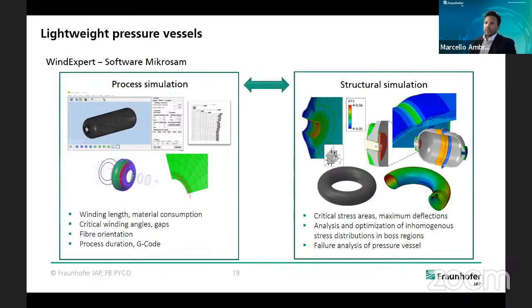So what we get from the process simulation is, for example, the winding length, the material consumption, critical wind angles, gaps, failures, the fiber orientation in each point, the process duration, and also the G-code for the machine. And in the structural simulation, we investigate critical stress areas and maximum deflections in certain regions of the pressure vessels. We also do optimization of the inhomogeneous stress distribution in the boss regions, and the failure analysis of the pressure vessel.